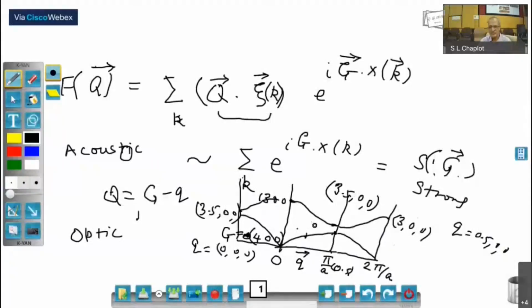This is probably not very clear, but I would like you to ask questions so that we can clarify again in a tutorial. The important things that we've talked about so far, in detailed phonon measurements: the first thing we mentioned is that it is important to see what the orientation of the resolution ellipsoid is, and we try to choose the vectors in such a way that we are parallel to the resolution ellipsoid.